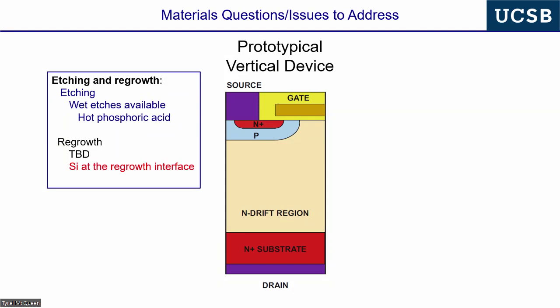You have lithography tools, right? And you have etching tools, right? And you have deposition tools, right? And the beauty of silicon and the beauty of most conventional semiconductors, gallium arsenide, indium phosphide, et cetera, is that they have beautiful wet etch technologies. When one goes to wide bandgap semiconductors like gallium nitride, silicon carbide, Mike, you can correct me, aluminum nitride, diamond, we don't have wet etch technologies. We have dry etch technologies.